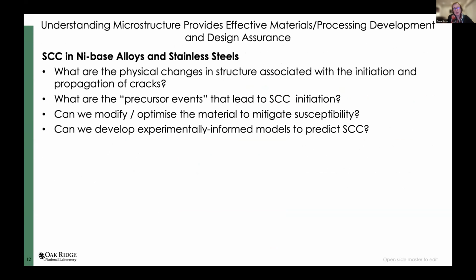So we've got stress corrosion cracking and irradiation damage. We're looking at stress corrosion cracking, and now we'll go through and show you some research. We want to know the physical changes associated with initiation and propagation of cracks. And we also are interested in knowing the things that we've not been able to understand up to this point. Are there precursor events that will lead to SCC initiation? Then the questions that come to mind are, can we modify or optimize the material to mitigate susceptibility? And can we ultimately develop experimentally informed models to predict SCC?